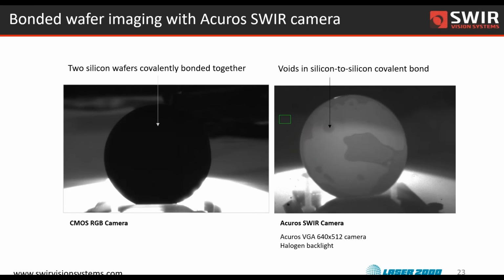Flipping the wafer again, there are many products these days, memory products, CMOS image sensor products, where wafer stacking is happening, where wafer to wafer bonding is occurring, either for packaging reasons or circuit density reasons. And so during this wafer to wafer bond process, voids can form. And in the visible region with the CMOS, you're not getting any light through. It just looks like a black opaque wafer. But in the shortwave IR with one of our cameras, you can see all of these voids where the bond between those two wafers was not as desired. I think this might be a particularly bad example of a bonded wafer, but it really does show you what can be seen with these cameras.